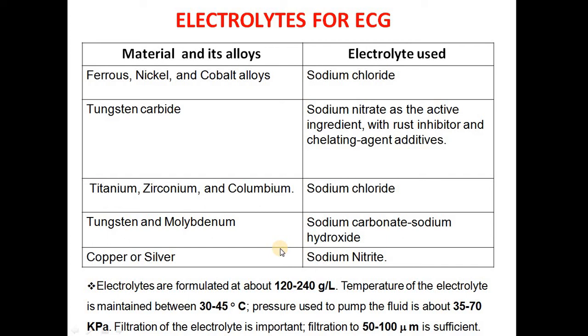So what are the electrolytes used for electrochemical grinding? For ferrous, nickel and cobalt alloys, we can use sodium chloride. For tungsten carbide, we can use sodium nitrate. For titanium, zirconium and columbium, we can use sodium chloride. For tungsten and molybdenum, we can use sodium carbonate or sodium hydroxide. For copper or silver, you can use sodium nitrite. The electrolyte temperature must be between 30 to 45 degrees Celsius, and the pressure used to pump it is about 35 to 70 kilopascal.